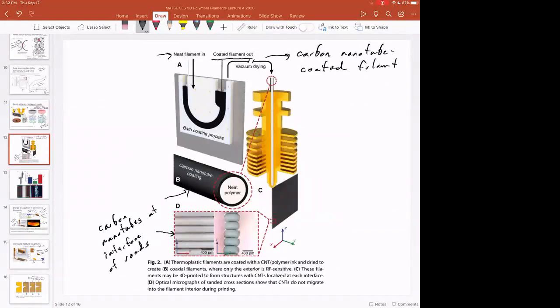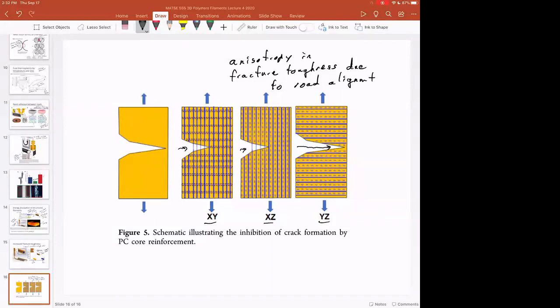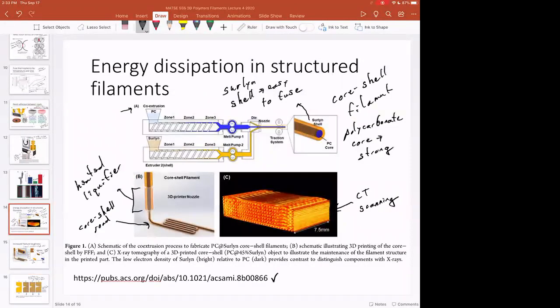So it's printed in a regular FDM style printer. You can never get threads of polycarbonate spanning the Z-axis. So when you look at the YZ, because you have layers in the Z direction, you can never get threads of polycarbonate spanning from layer to layer. And so your fracture toughness is always going to be lower in that direction because you're not trying to fracture any of these polycarbonate threads as the crack propagates. So that's just some really interesting things you can do with road alignment. That's some really interesting things you can do with composite filaments.